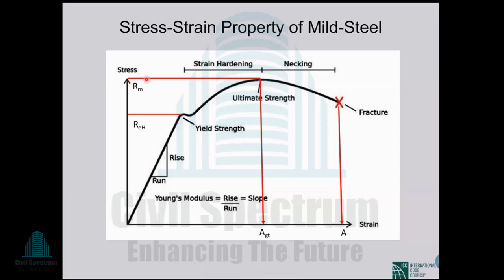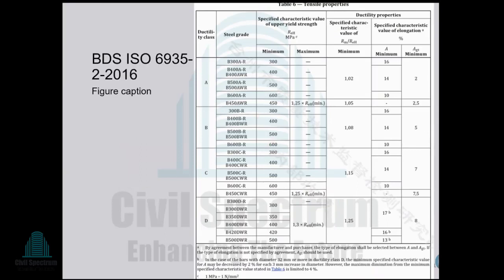It is found that if this T/Y ratio or Rm divided by Reh ratio is high, then naturally the ductility of the steel is high. So instead of calculating ductility in terms of strain, ductility is defined in ISO in terms of this ratio, Rm divided by Reh, or T/Y ratio. So you see, for ductility class A, this Rm divided by Reh is 1.02, only 2% more. Ultimate strength is only 2% more than yield stress. Ductility class B is 1.08, ductility class C is 1.15, and ductility class D is 1.25.